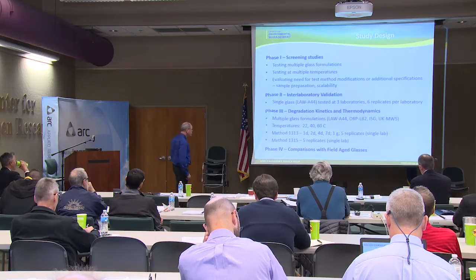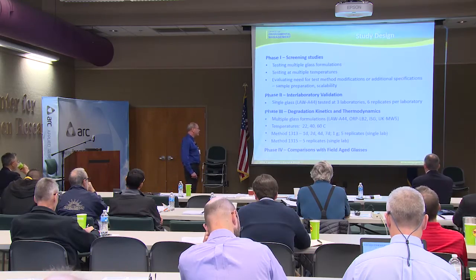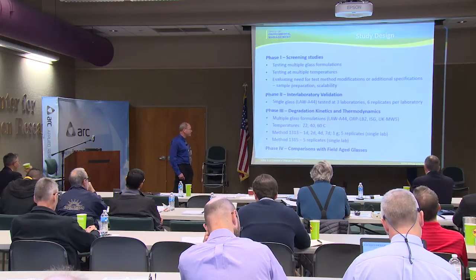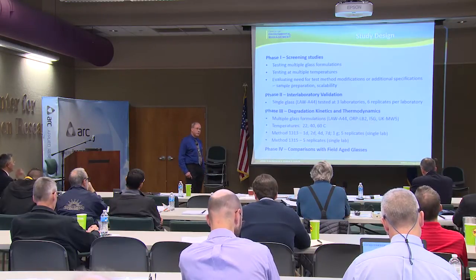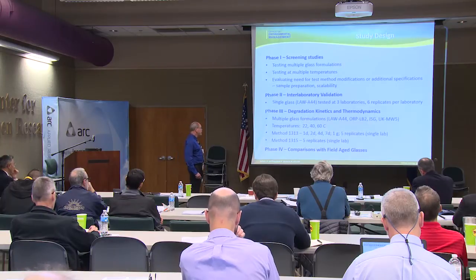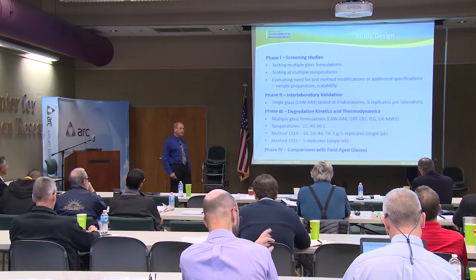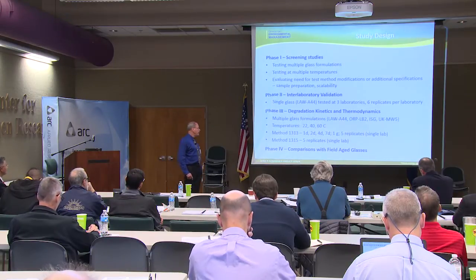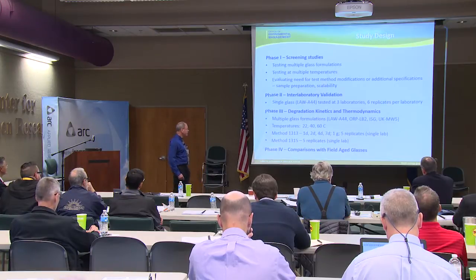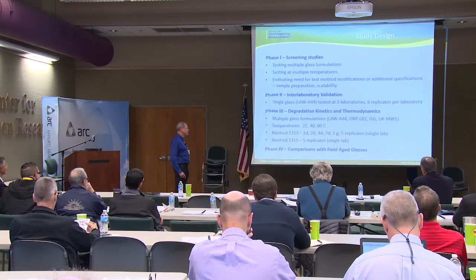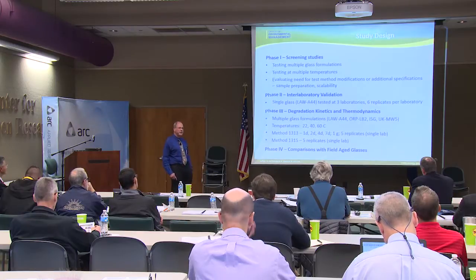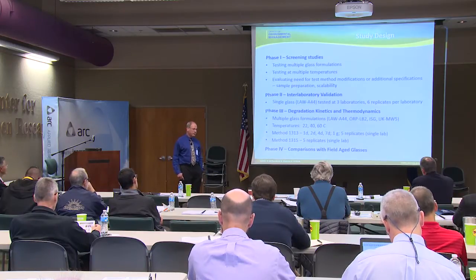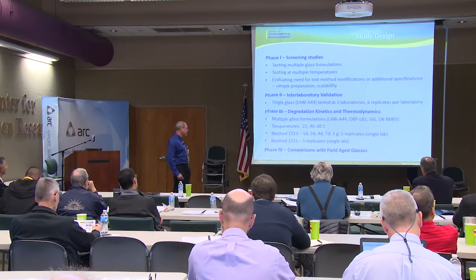So for method 1313, we looked for the kinetics at 1 day, 2 days, 4 days, 7 days, contact intervals. And then 1 gram glass for each test position aliquot, and 5 replicates, and a single lab for each glass. So it was basically divided up amongst the labs to carry out this campaign of testing on the different glasses.